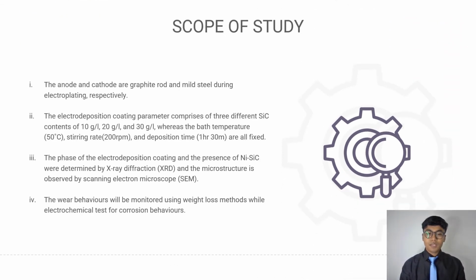For the scope of study, firstly, the anode and cathode are graphite rod and mild steel during electroplating respectively. And the second, the electrodeposition coating parameter comprise of 3 different silicon carbide contents of 10 gram per liter, 20 gram per liter, and 30 gram per liter. Whereas the bath temperature, stirring rate, and deposition time are all fixed, which is the bath temperature is 50 degrees Celsius, the stirring rate is 200 rpm, and the deposition time is 1 hour 30 minutes.